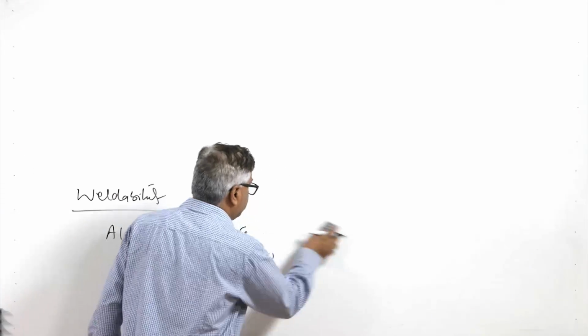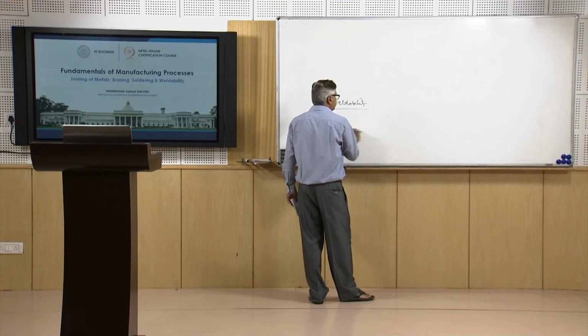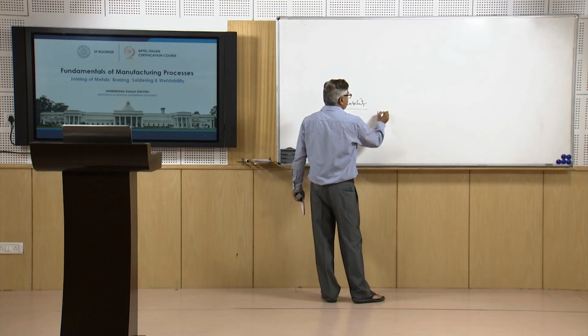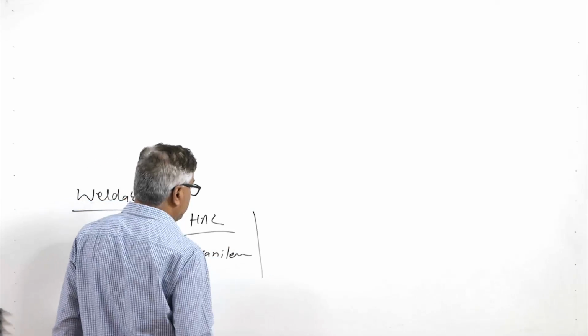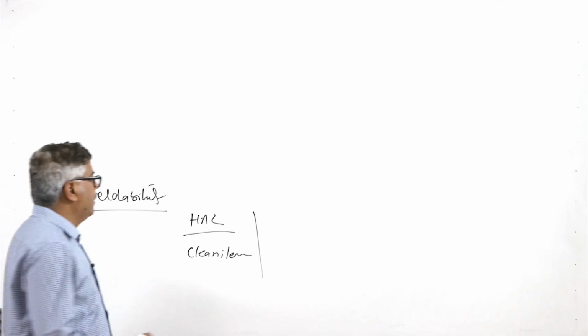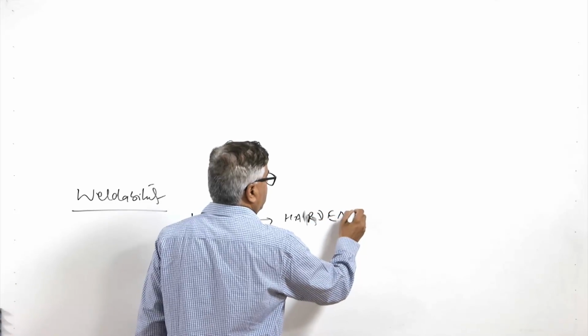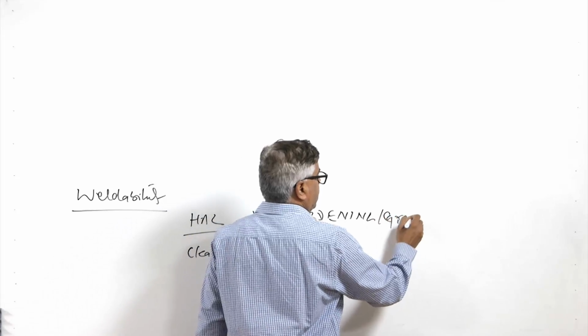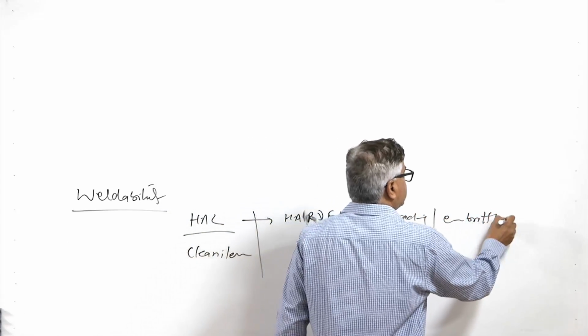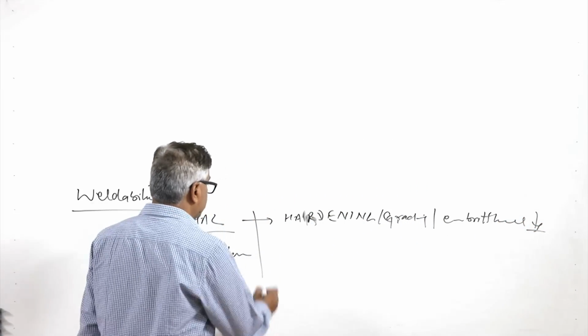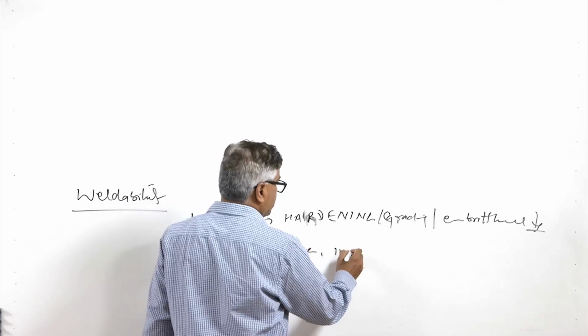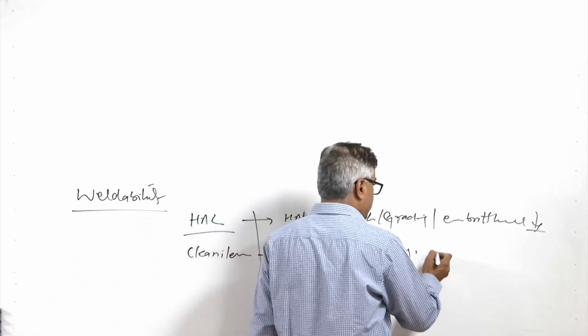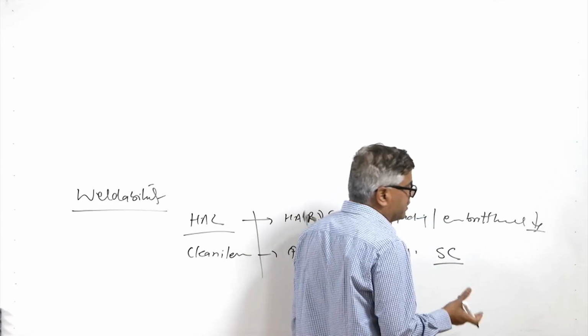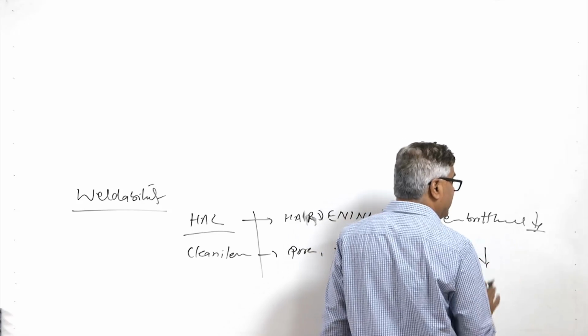For defining the weldability of steels, it is somewhat easier, because basically two aspects are looked into: the way in which the heat affected zone of the steel behaves and the cleanliness of the weld which is obtained. So, if the heat affected zone is more problematic in terms of hardening, cracking, embrittlement, all these will lead to reduced weldability of the weld joint. On the other hand, the presence of pores, inclusions, slag, solidification cracking due to the presence of low melting point things like silicates, etc., will also lower the weldability of the steel.